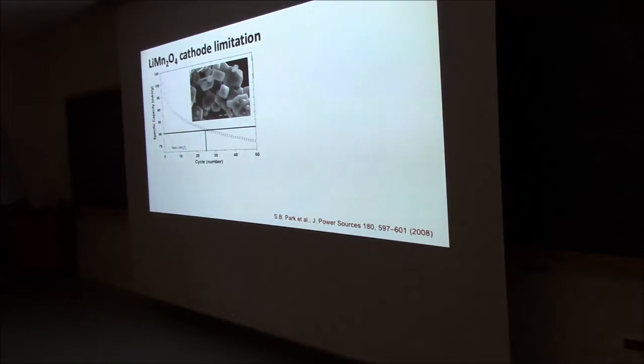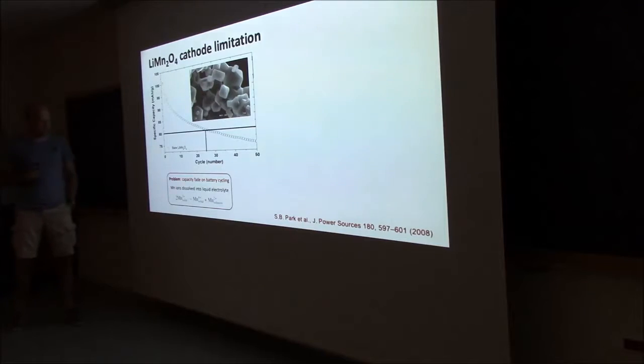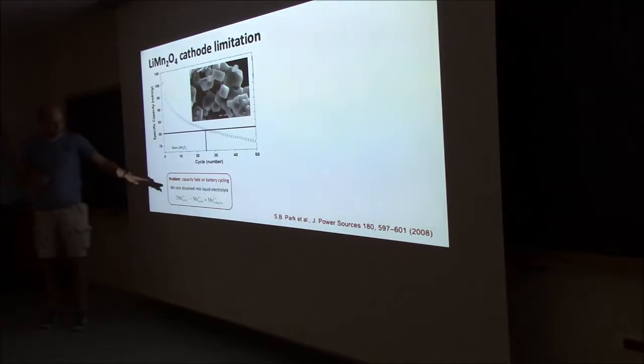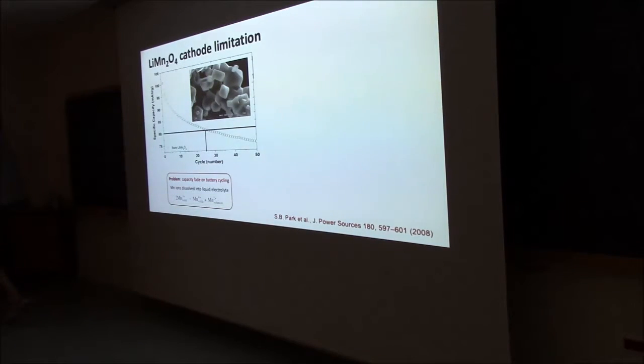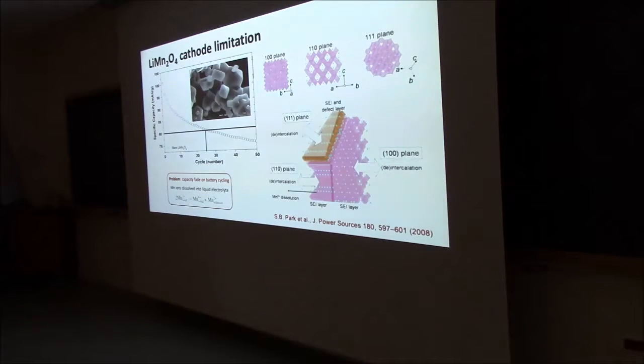It's gone. So you will never use that in a real application. And there have been some studies where they say, okay, the problem is that the manganese will dissolve into the liquid electrolyte. And the manganese, during charging, discharging, goes into different valence states, and at a specific moment it is possible to dissolve. And the thing that was predicted is it really depends on your crystal facet.